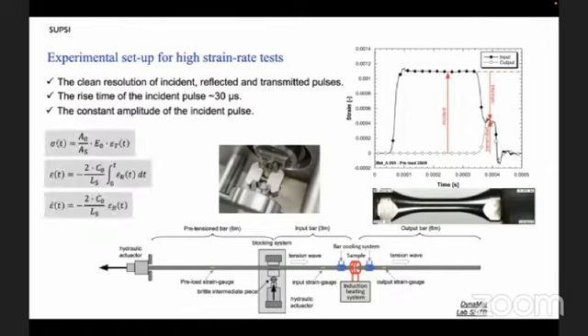The tests we have carried out at a high strain rate were at room temperature and elevated temperature. For the latter, thanks to the induction heating system, we are able to heat up the sample to elevated temperature, obtaining a picture like this one.